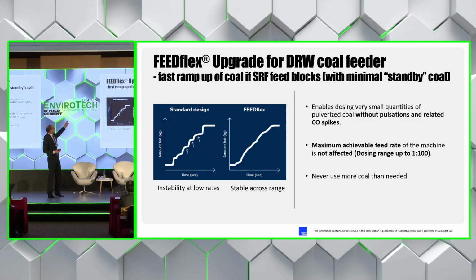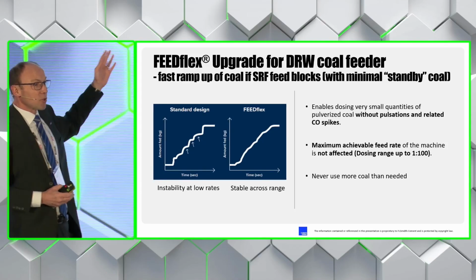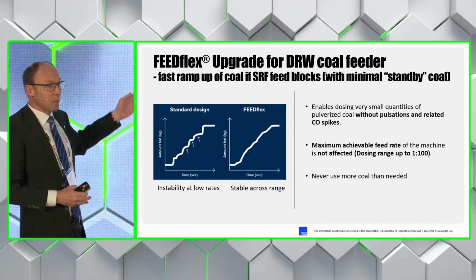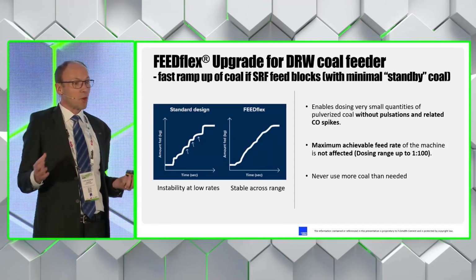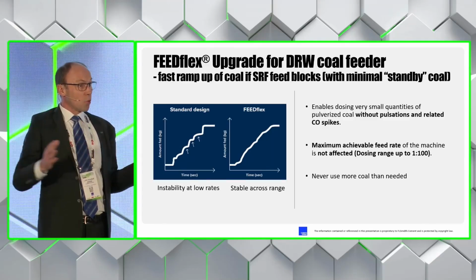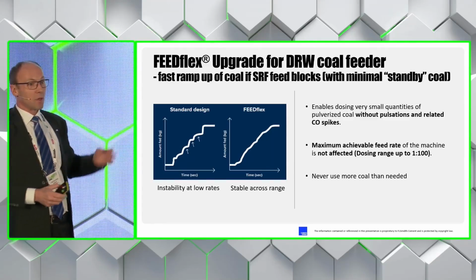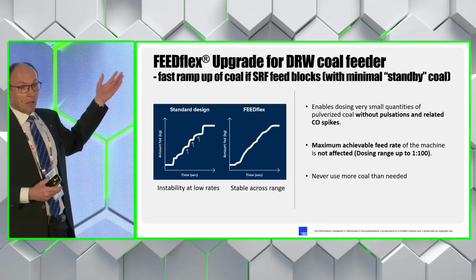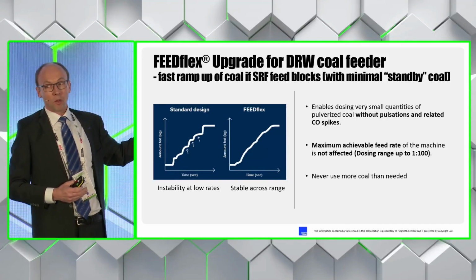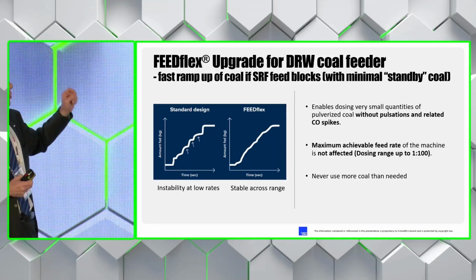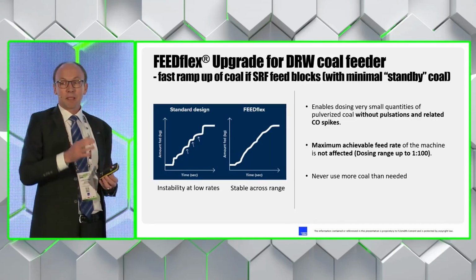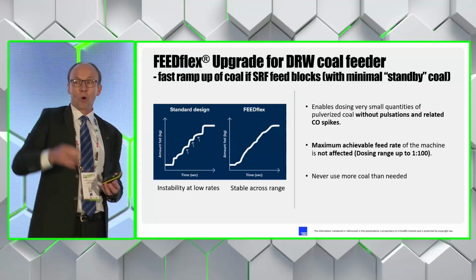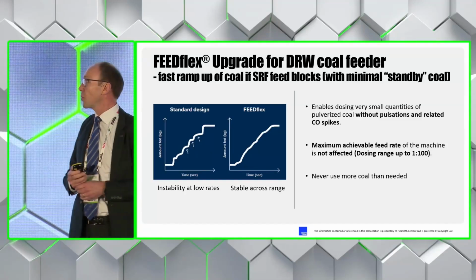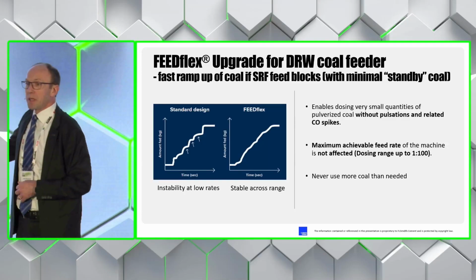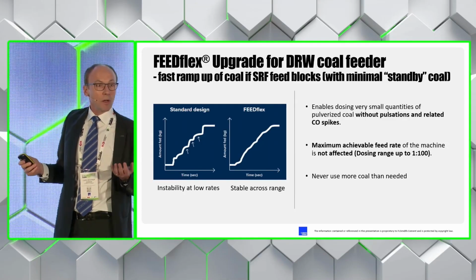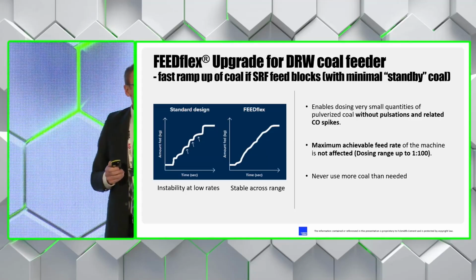At the beginning of last year, Mannok installed a FeedFlex upgrade to the coal feeder, which means now the turn-down ratio for the coal feeder changed from 1 to 10 to 1 to 100, which means now they could operate with 99% alternative fuel in the calciner and then have the 1% coal as standby coal, but they still didn't lose the ability to ramp up the coal quickly to replace these alternative fuels. So this was really good, and now it meant that they could run with 99% substitution in the calciner and